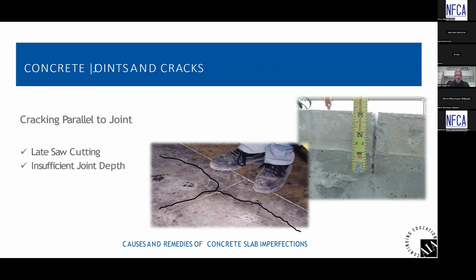And on the right is just an example of a really nice deep joint. Looking at the thickness of this joint being 3 inches deep, it's probably concrete that's somewhere around 10 to 12 inches deep. The saw cut needs to be roughly 1/4 to 1/3 of the slab thickness to be able to create a relief break for when the concrete shrinks. So if your saw cut is not at least 1/4 to 1/3 of the thickness of the slab, then the depth of the saw cut's not good enough, and it's not going to do you any good. So a typical 4-inch slab should have a saw cut that's 1 inch to 1.5 inches, somewhere in that thickness, to allow for a break at the base of that joint.